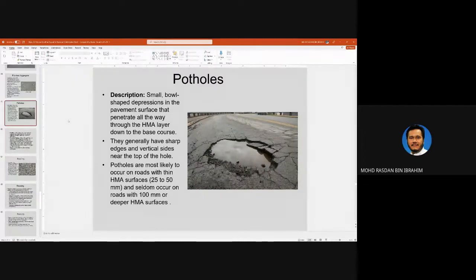Potholes, small bowl-shaped depressions in the pavement surface that penetrate all the way through the HMA layer down to the base course. Usually, it occurs because of crocodile cracking. It starts with crocodile cracking and you don't repair it. So that crocodile cracking, the pieces become dislodged and it becomes a pothole. Once it becomes a pothole and you have water in the pothole, meaning that water will travel until the base course. Once you have that, you need to remove everything, including the road base. Replace everything and then repave the pavement. It will not work just to cut one area and then patch just that area. So the entire pavement here needs to be revamped.